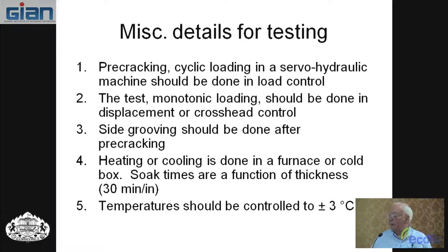Some of the specimens use side grooving. Side grooving is often used by putting a groove on the side of the specimen to keep the crack front straight. If you're going to do side grooving, you should do that after pre-cracking. If you do it before pre-cracking, you can get cracks to run down the side groove.